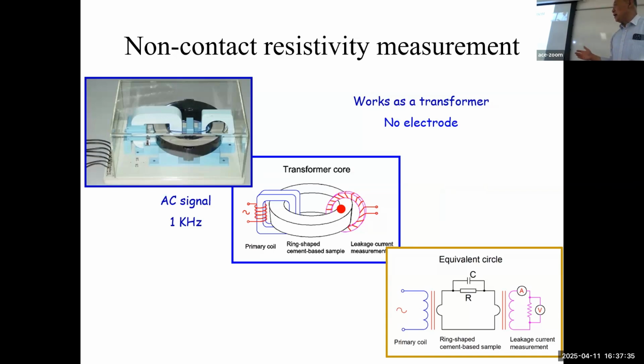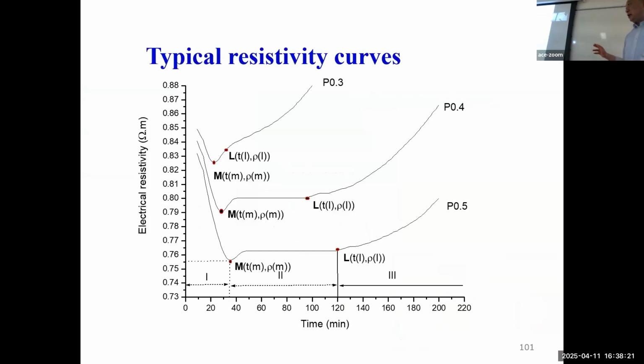So I developed this non-contact method based on an electromagnetic mechanism. Basically, we have something like a transformer with an iron core that generates a magnetic field in the core, and this magnetic field generates an electric field in a circular ring. This circular ring is made of concrete or cement-based material, and then we use a non-contact current meter to measure the current, so the whole thing has no contact.